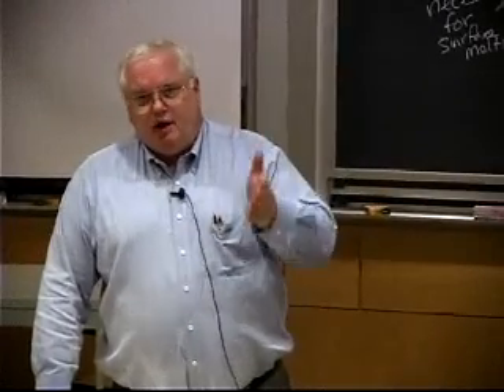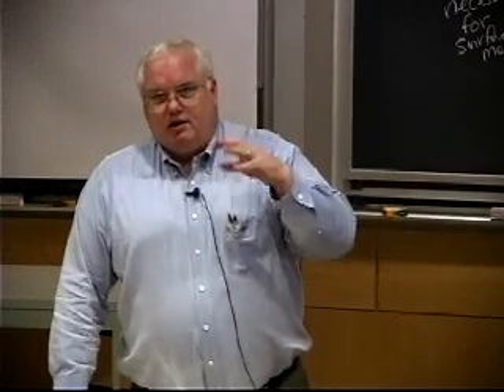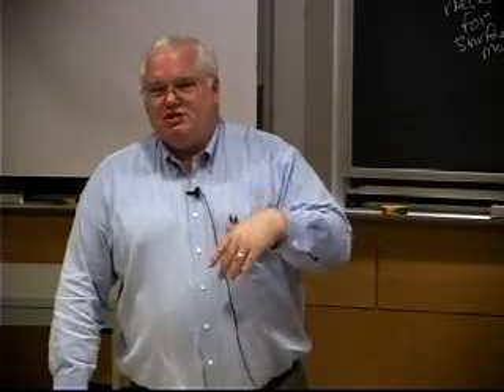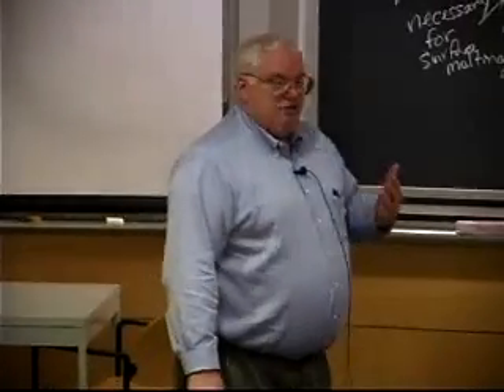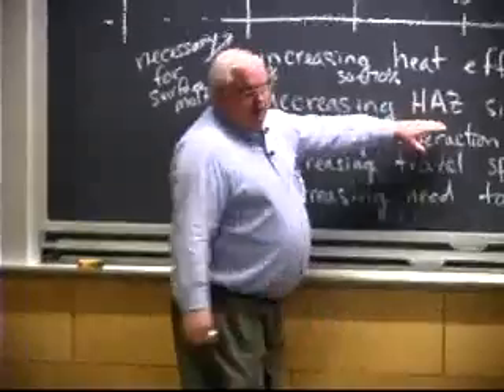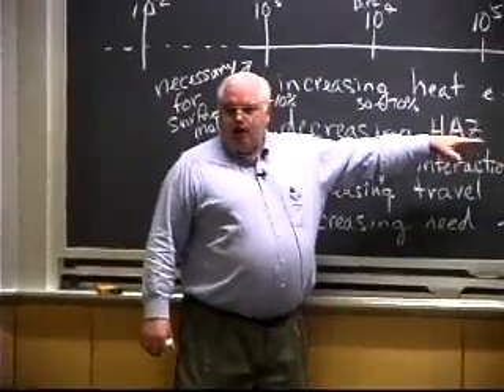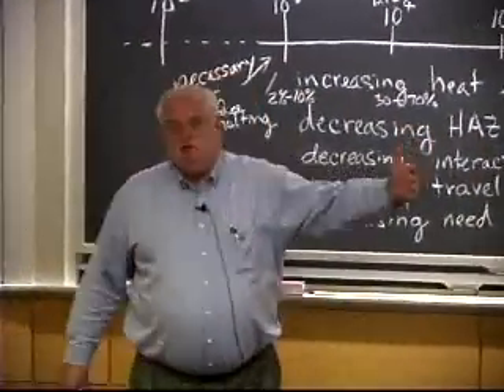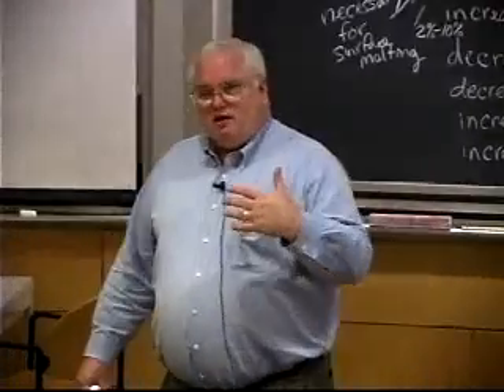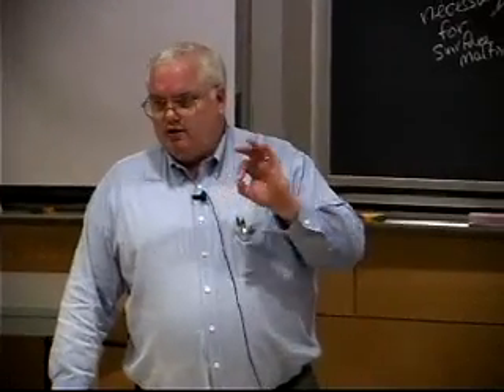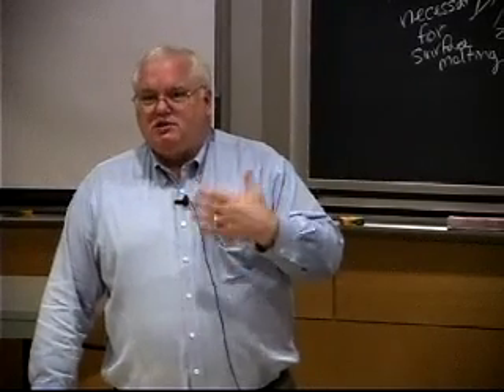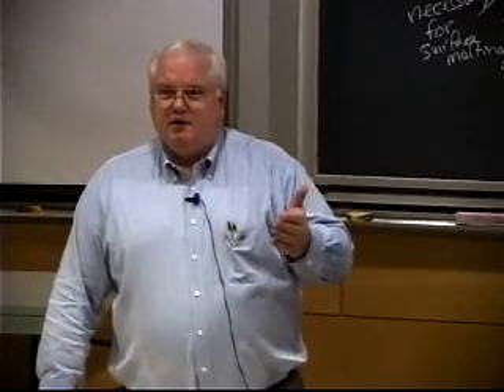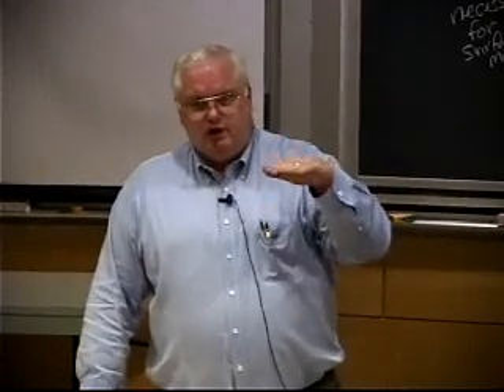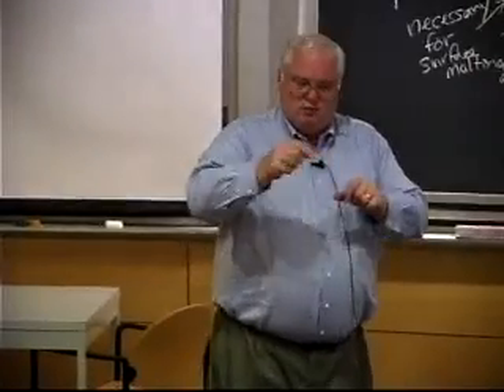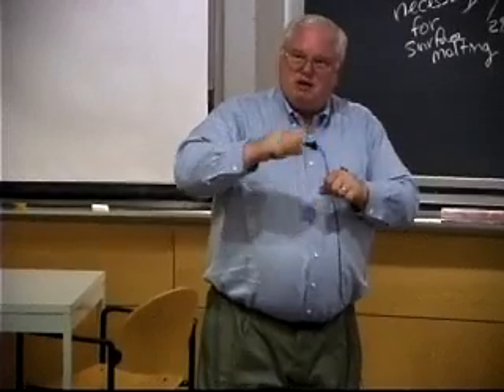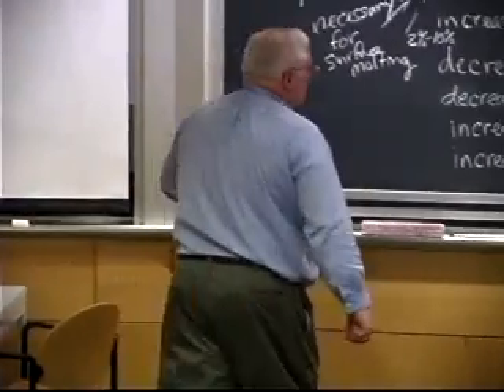It's an area that was heated above, in that case, 700 degrees centigrade, changed its crystal structure and transformed, and it etches differently afterwards. It also has a different microstructure and different mechanical properties. So people are interested in heat affected zones. Sometimes they want to make them as small as possible, such as in welding most steel or aluminum, but sometimes they want to make them as large as possible, such as welding the chrome moly steels in nuclear utilities, because in that case the steels need to be tempered, heated up, not to melting again, but to an intermediate temperature. And so the bead, if you're putting a multi-pass weld bead on, you want the bead on top to temper the bead underneath. And so you want a big heat affected zone.